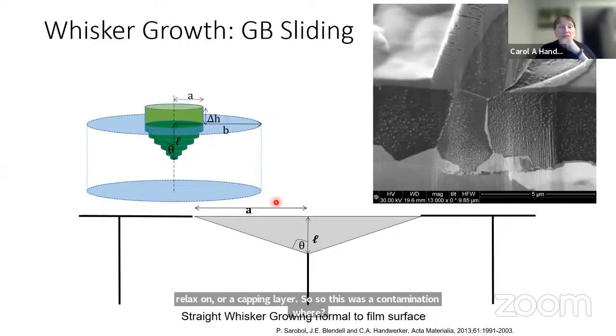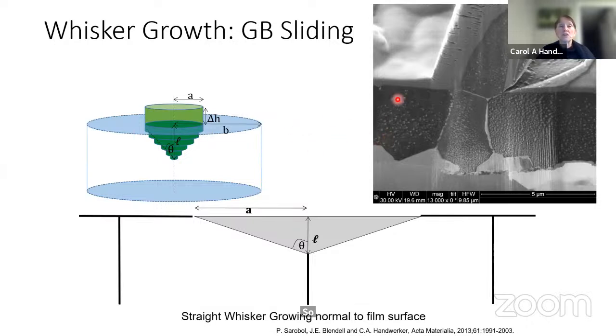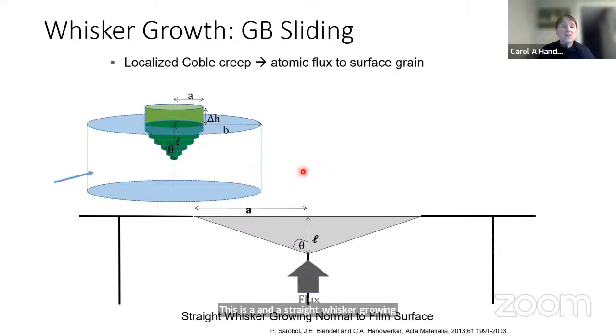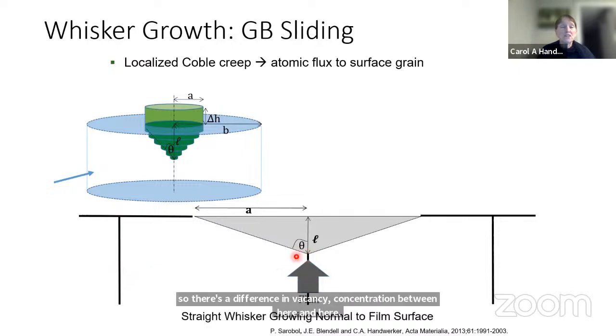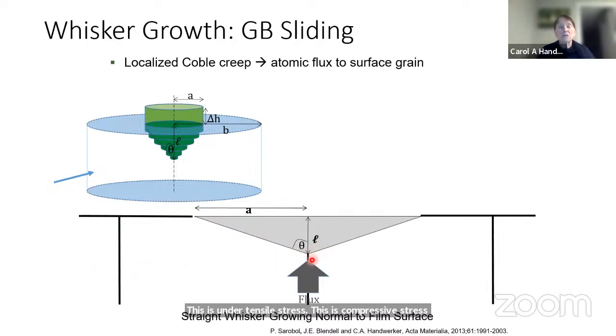So let's transform this to whisker growth, where we have a shallow grain. Instead of a cylindrical grain, this is a schematic of what a shallow grain would look like in the film, and a straight whisker growing normal to the film surface. So we have, again, compressive stress. The position here, on the free surface, is under tensile stress relative to these boundaries. And so there's a difference in vacancy concentration between here and here. This is under tensile stress. This is compressive stress. So there are more vacancies here than here. So the vacancies migrate here, the atoms move here, and this is how the whisker grows.